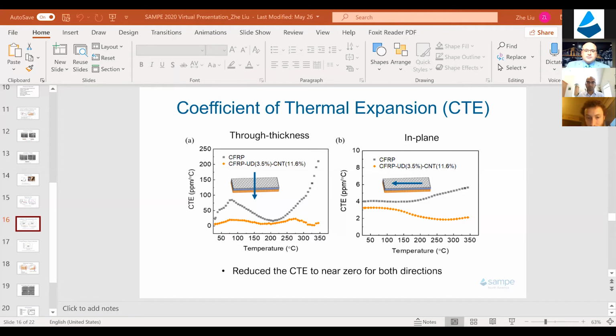Yes. Actually, we didn't test interlaminar shear. For the composite ASTM standard to test interlaminar shear, the sample thickness is around 6 millimeters, but for our composite, the thickness is only 1 millimeter. So instead of interlaminar shear, we tested the coefficient of thermal expansion to check for delamination with temperature going up. Also, we tested the mechanical property of the composite using 3-point bending.